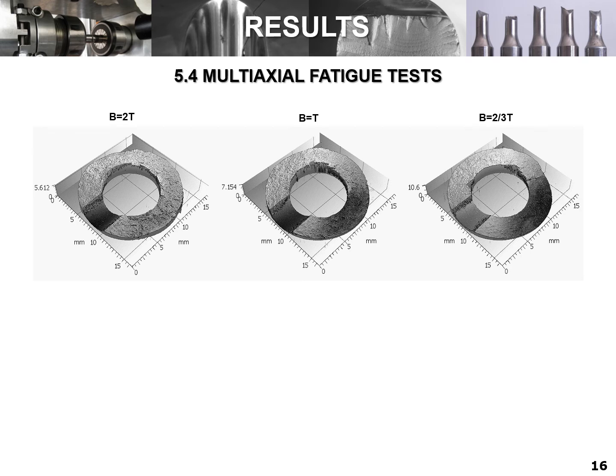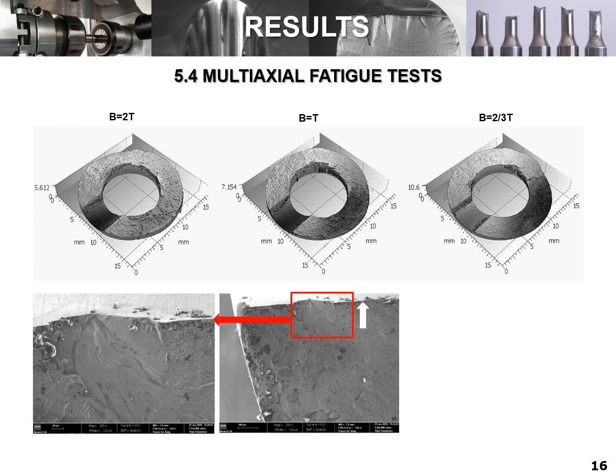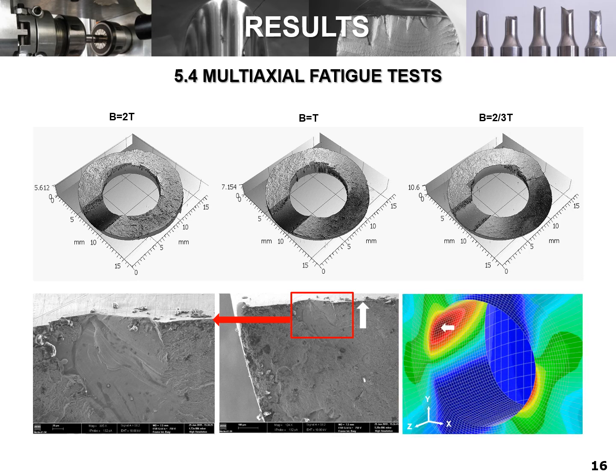As we can see, they tend to be flatter for lower levels of shear stress. Examination of the fracture surfaces by scanning electron microscopy suggests that unmelted regions were the main source of crack initiation. It is also clear from the micrographs that fatigue crack initiation sites are located at the whole surface, near the outer diameter of the specimen. These points are close to those predicted by the finite element simulations, white arrows, based on the node with maximum value of the first principal stress, as suggested before.